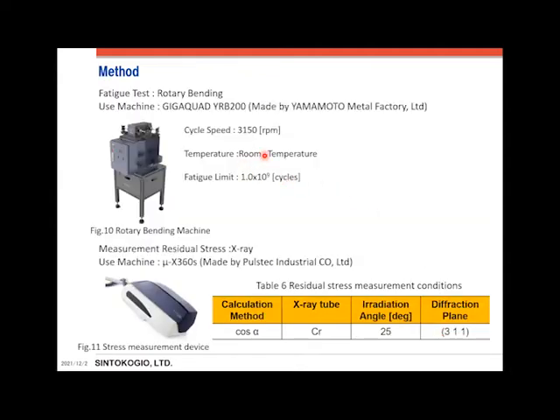This page shows the method of fatigue test and the measurement of residual stress. A rotary bending test was used to evaluate fatigue. The cycle speed was 3,150 RPM. The test was performed at room temperature. The fatigue limit was set at 1 gigacycles. The residual stress values were evaluated using an X-ray residual stress measurement system. The condition is shown in table 6.